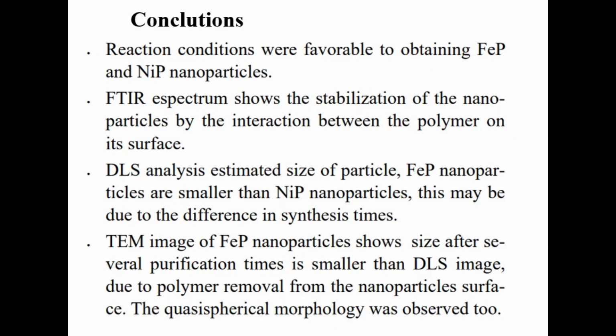The image of iron phosphide nanoparticles shows the size after several purification times is smaller than the DLS image due to polymer removal from the nanoparticle surface. The quasi-spherical morphology was observed too.